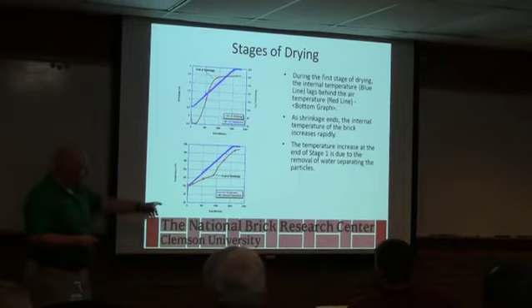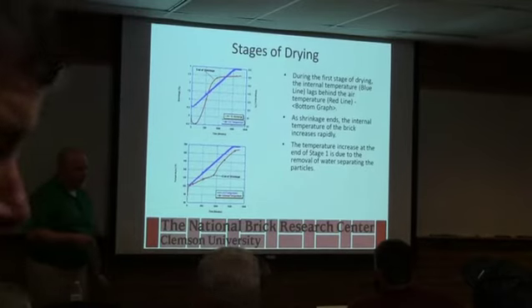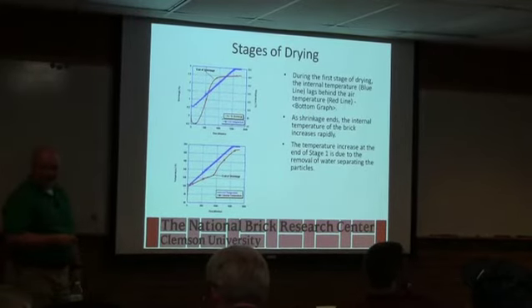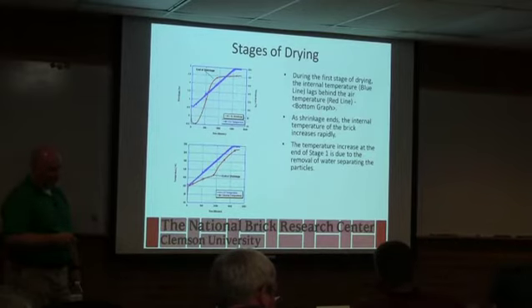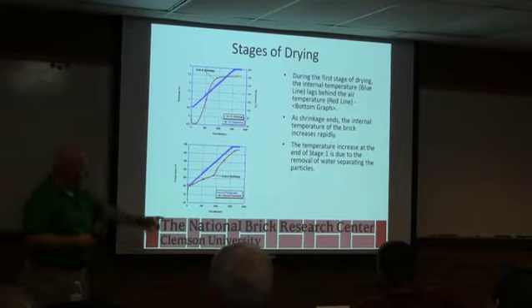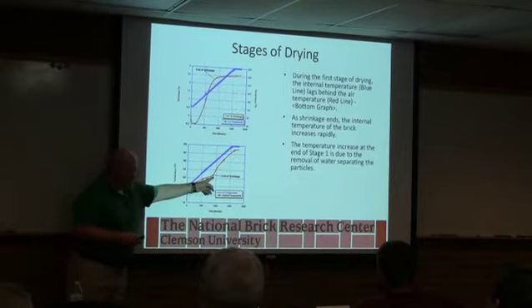It'd be interesting, too, if you could check different spots on your car. Oh, I've done that before. And it's just depending on the part of the dryer and the condition of the fans, in a certain area you can get very wide variation, from the top of the stack, which is like, say, three stories, to the bottom. You have like a 10, 15, 20 degree temperature swing. But exactly, wherever you see that break point, that's where shrinkage has stopped.